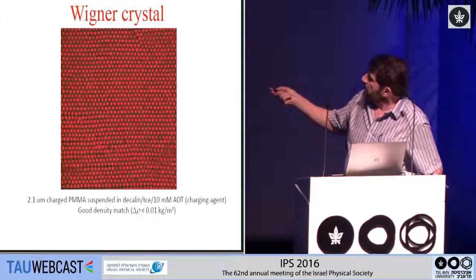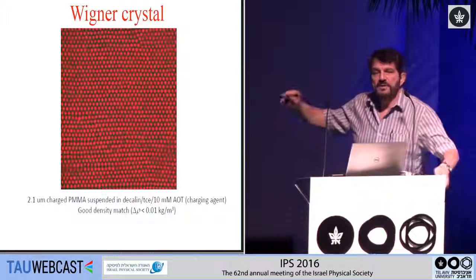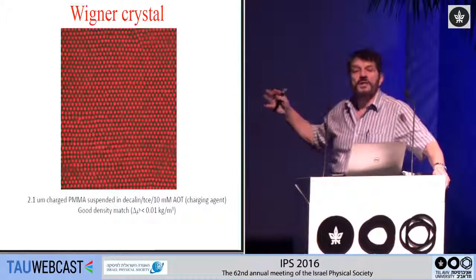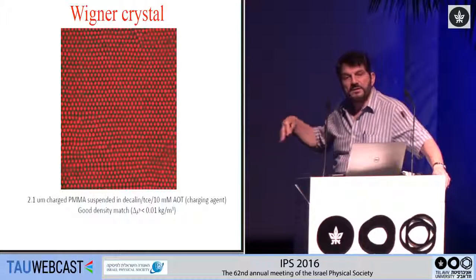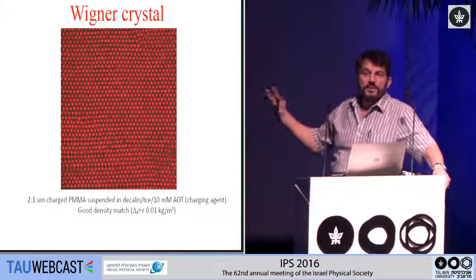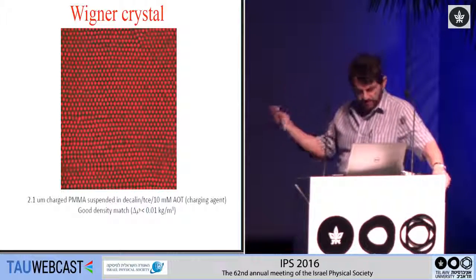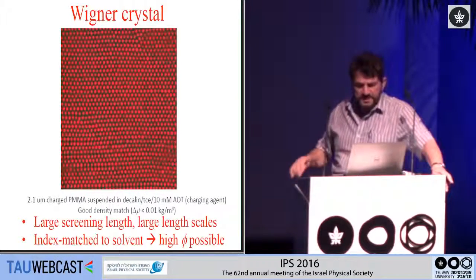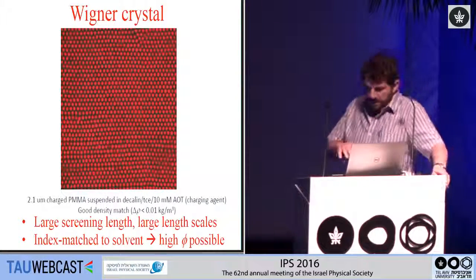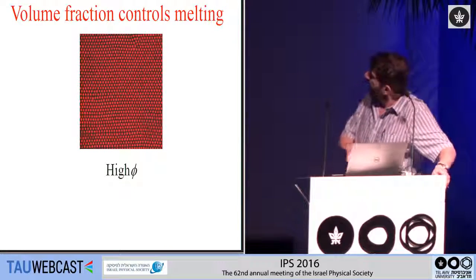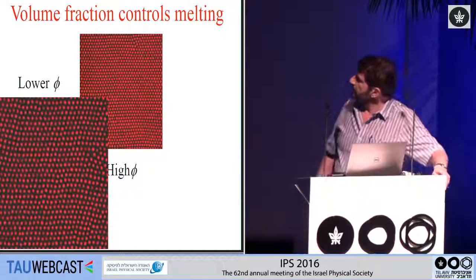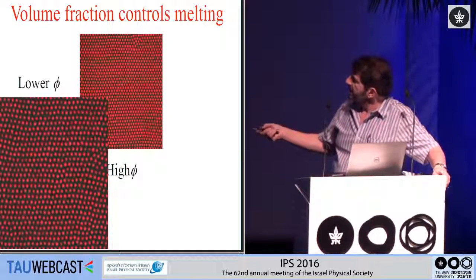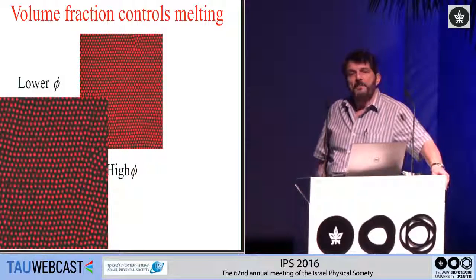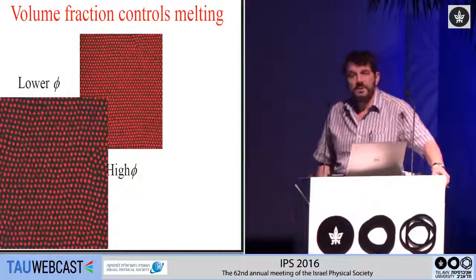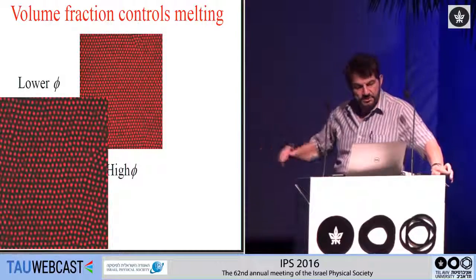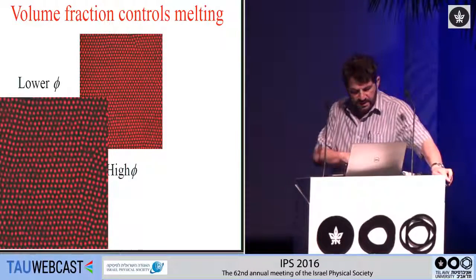If you look carefully, you see that this is actually a movie, and the particles are undergoing fluctuations. There are actually some phonons that you can see in the system. The particles are thermalized, they fluctuate, but they remain spatially in the same location. They're a crystal lattice. You can raise the temperature by going to a lower concentration, and this is what a somewhat lower concentration, so a higher temperature, looks like. And now you can see that the fluctuations become much larger in magnitude, and the separation between the particles, of course, gets larger as the effective temperature gets higher.